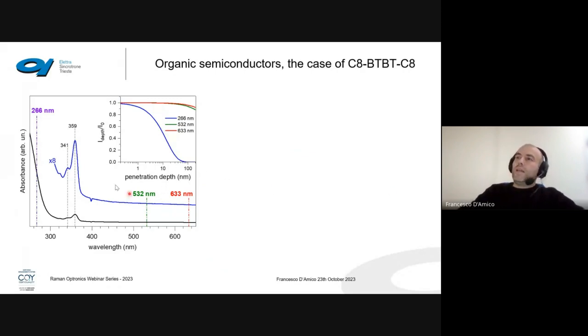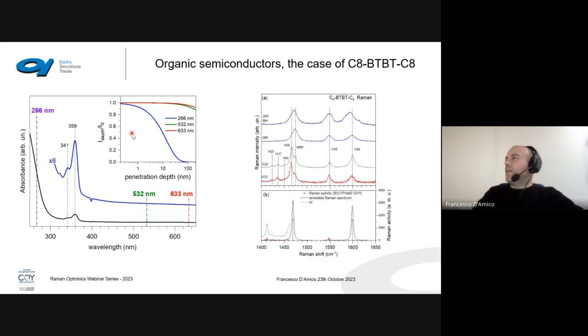This is the absorption spectrum of our film. The penetration depth depends on the excitation. When we go at 633 nanometer, 532 nanometer, we have a higher penetration depth. But at 266 nanometer, we have a very small penetration depth, and therefore we are analyzing only the surface layer of these films. And this is also reflected in the spectrum, because in the higher part of the spectrum we can see differences basically related to the resonance.